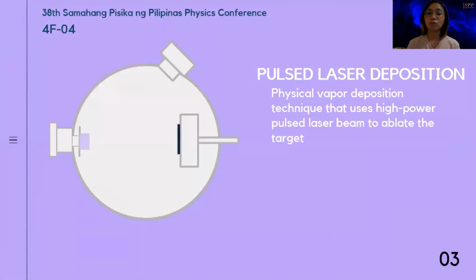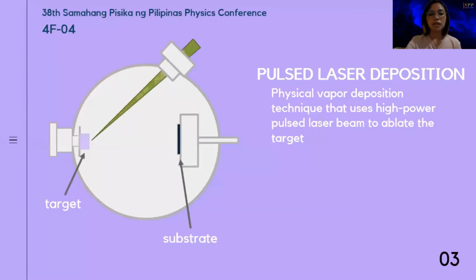Now we move on to the process of producing thin films, which is pulsed laser deposition. This is a physical vapor deposition technique that uses a high-powered pulsed laser beam to ablate the target. PLD is a common way to produce thin films due to its capability of stoichiometrically transferring the target to the substrate. This is a vacuum chamber with the target attached on the target holder and the substrate on the other end. When a laser emits optical pulses, energy is transferred to the particles on the surface of the target, which results in the ejection of highly energetic particles, which creates the plasma plume. These ejected particles travel from the target to the substrate and condense on top of the substrate.